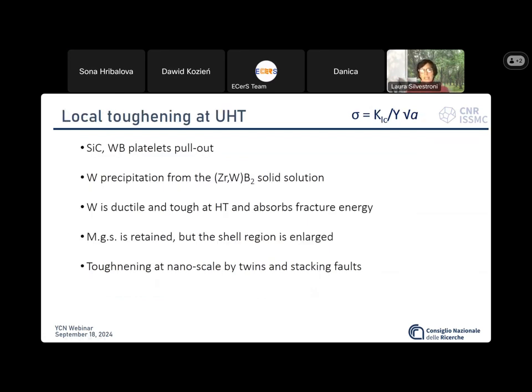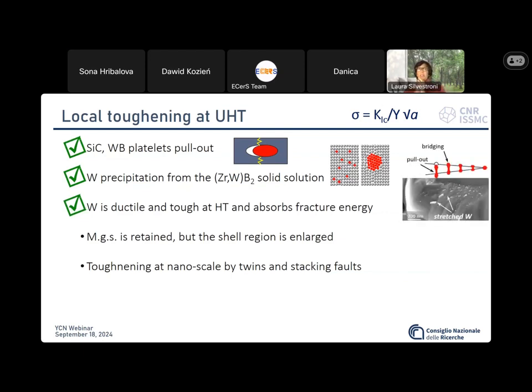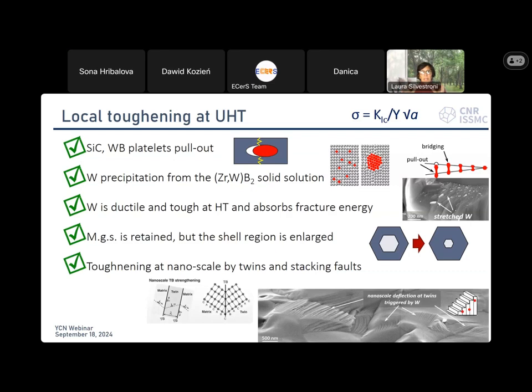We also hypothesized local toughening occurring at ultra-high temperature, including silicon carbide and tungsten diboride platelets pull-out. We had tungsten precipitation from the (Zr,W)B2 solid solution. And this rejected tungsten is ductile and extremely tough at high temperature, so it could absorb fracture energy. We also considered the mean grain size that was retained during the test at up to 2100 degrees C, but actually the shell region enlarged. So a larger volume fraction of material was reinforced by these precipitates, and the similar toughening at nanoscale in the shell was amplified.